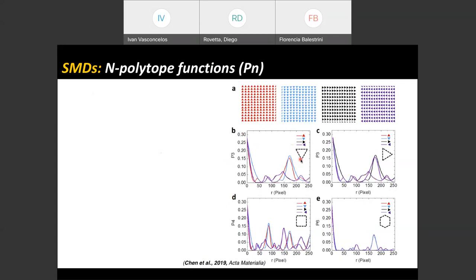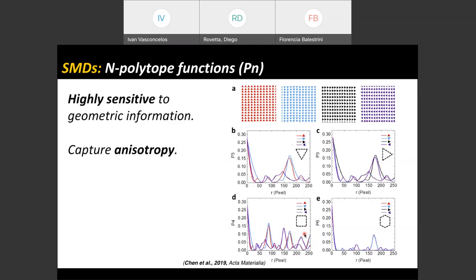Notice for when we pick the polytopes that are vertical triangles, they peak at the volume fraction as they should, they decrease exponentially, but then they peak again at a distance. That's because for both this material here and that material here, because the triangles are vertically oriented, we can fit bigger triangles into them at larger distances. Likewise, the same thing happens for the colors here that you see that have horizontal triangles. As we increase the order of the polytopes, these curves also look more complex. And this means that we can capture here geometrical information with a high degree of sensitivity, and we can also capture anisotropy, right, at relatively little computational cost, because these scale with a single parameter.